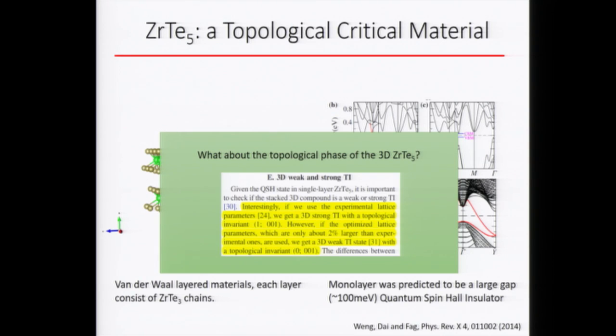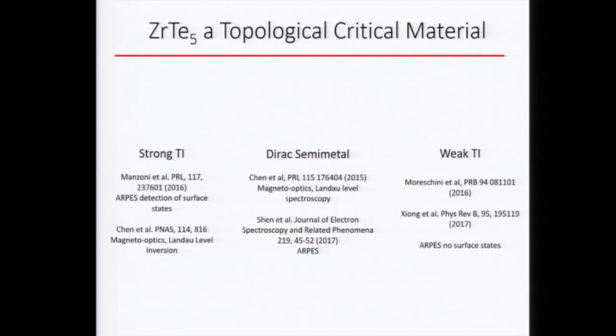But in this initial paper, they immediately found that this question is quite tricky, because when they do the calculations, they can use an experimental lattice constant or a relaxed lattice constant in the DFT calculation, and for each case they found a different answer. For one case, they get a 3D topological insulator with these topological indices. For the other case, they get other topological indices, corresponding to a weak topological insulator. So this is why you have so many confusing experimental results.